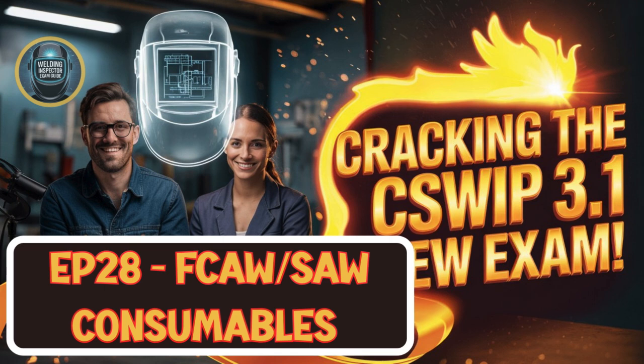Right. Second, we have butt joint cored wire. This is made from a strip of metal that's bent around the core powder, and the edges are simply brought together, butted up against each other, maybe with a slight weld or seal. This type offers pretty good resistance to moisture pickup, though perhaps not quite as foolproof as seamless. It can also be copper-coated. Like the seamless type, it tends to have a fairly thick sheath. The potential issue is that it can sometimes be difficult to get a perfect seal along that butt joint during manufacturing, which could be a potential entry point for moisture over time.